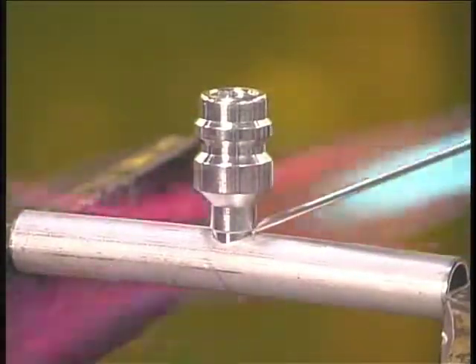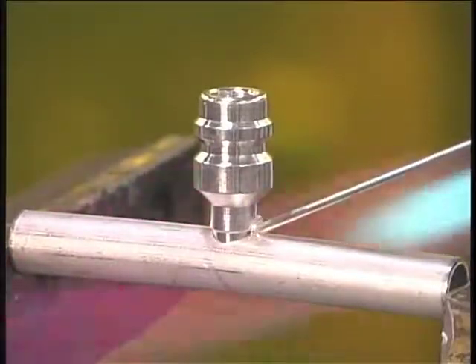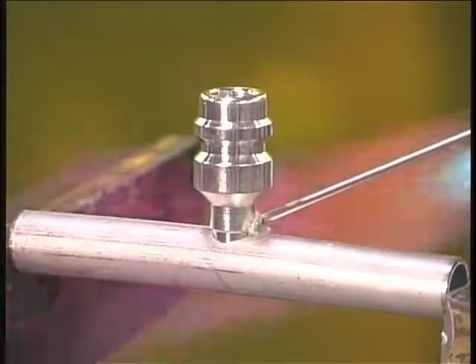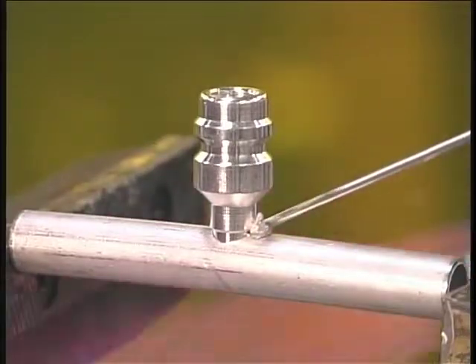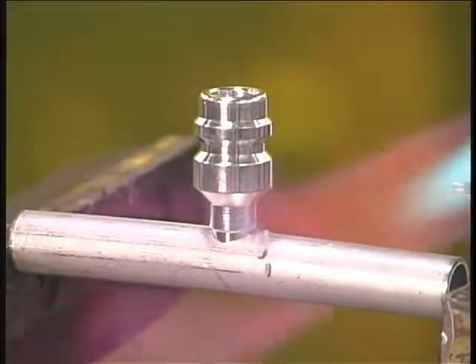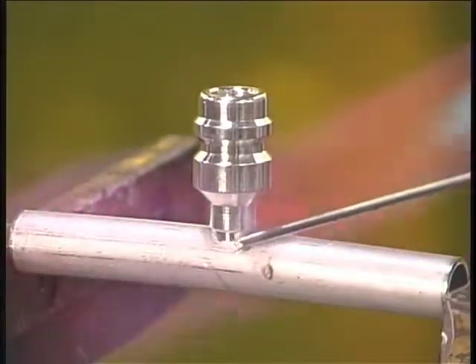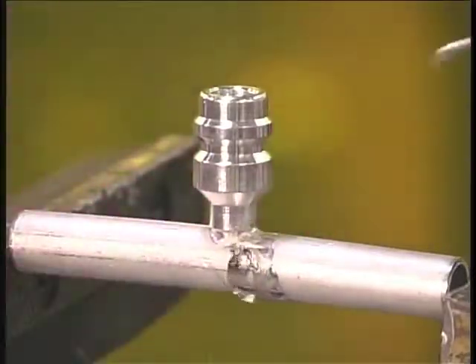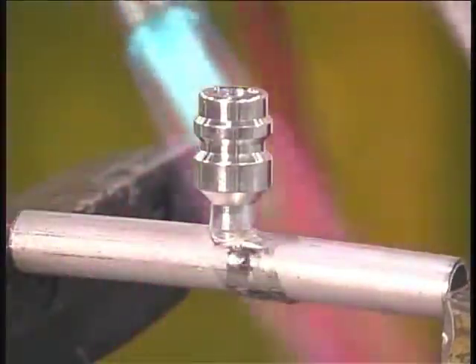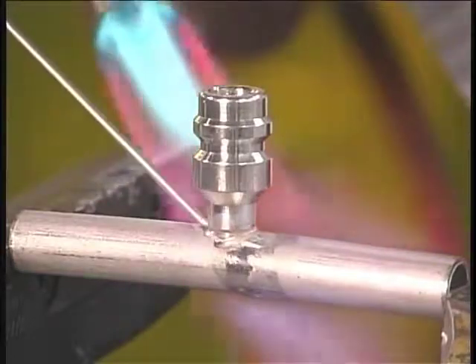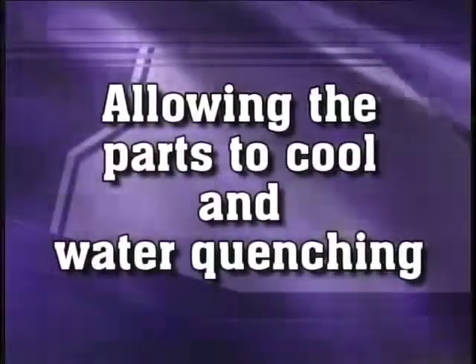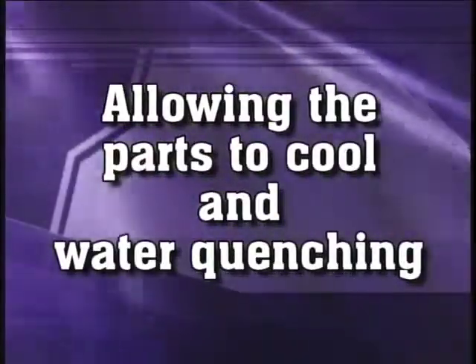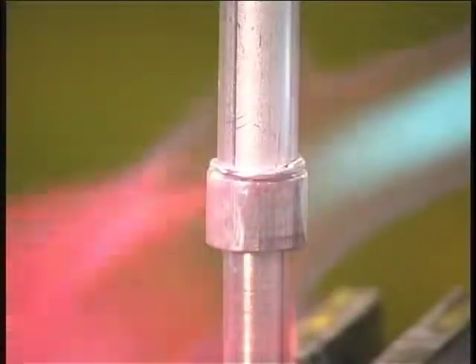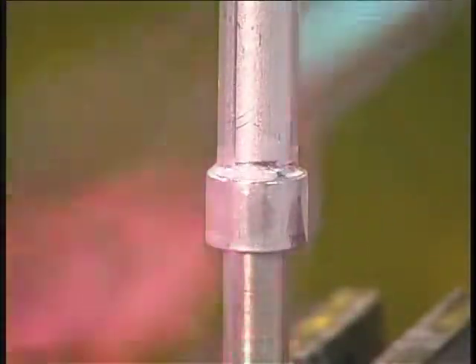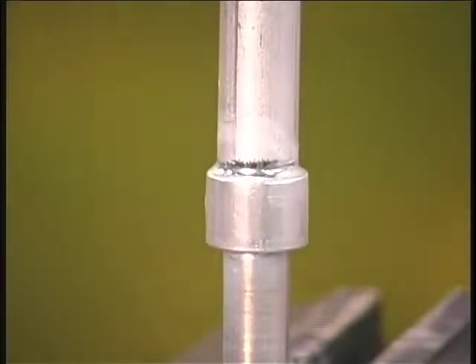Keep moving the flame around as the orange glow gets brighter. This is the point where the flux begins to melt and lift the oxide layer away. As the filler metal begins to melt and flow, continue applying heat with the torch for a couple of seconds until sufficient filler material has been drawn into the joint. Remove the torch heat as soon as enough filler metal has been drawn into the joint for a full fillet.